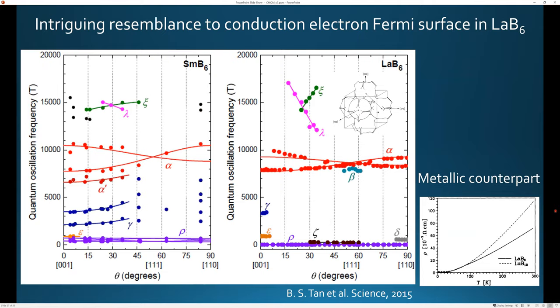What I was trying to ask is that from my experience of working on nodal line semimetals, like model-wise calculations, I know that for some materials like ZrSiS, the Fermi surface is just like a torus at low energies. And then if you have two fundamental frequencies, in the FFT spectrum you get two peaks. So compared to that, I see that here the Fermi surface is quite scary looking. So in this case, how many fundamental frequencies will there be? Right. So I think this comes back to the fact that it looks like a metal, but it doesn't look like good enough a metal to give you many harmonics.